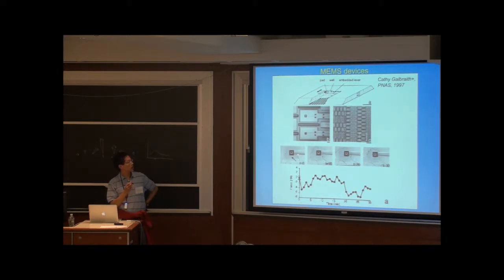So what happens is that now when a cell, I don't know if you can see this, there's a cell sitting here that's just started to crawl up to the top of this cantilever. And when the cell starts to crawl over it, it is forming adhesions on that cantilever. And you can see that as the front of the cell is going over it, you see this force that comes up, and you can measure the force over time as the cell is crawling over this thing. That force measurement is direct, right? It's not calculating something that you're guessing. You're just looking at the deflection of the cantilever, and that backs out the force. So that was, in my mind, a key breakthrough in this field.